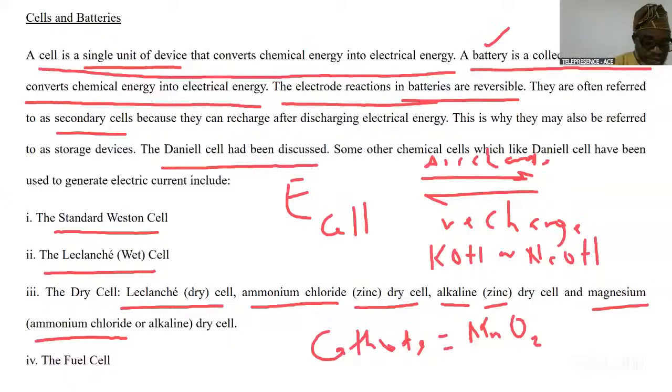One of them is ammonia gas, which can stick on the surface of the cathode and thus reduce the efficiency of the cell. The ammonia in the presence of zinc ions can turn to a crystal called zinc diammine. This crystal can clog the zinc rod, thus keeping the cell from optimal efficiency.